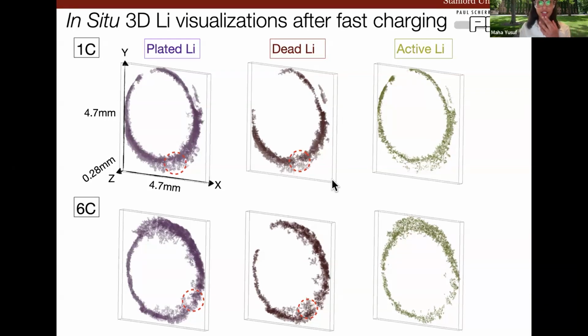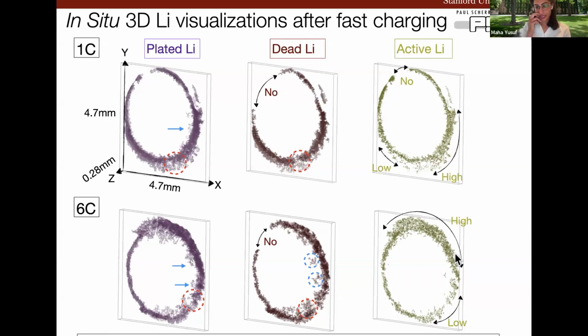So for example, this data clearly shows that there are these protrusions, which are lithium, like these tiny sharp lithium structures, which are forming around this edge at a faster charging rate, and they are absent or minimally present at a lower charging rate. And there are parts of the battery which form no dead lithium or very minimal active lithium, and parts of the battery that form low and high active lithium. So this data clearly demonstrates 3D spatial heterogeneities in the formation of plated, dead, and active lithium, and also morphological differences between low and high charging rates.